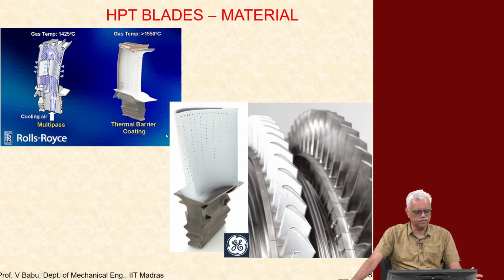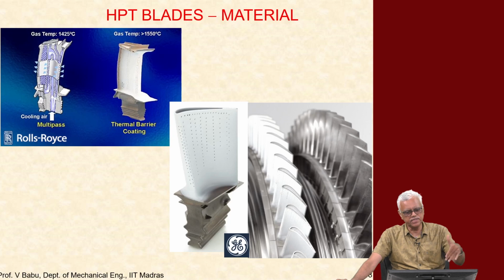So, the cooling plus the TBC. So, you can see the TBC blades, you can see the hollow blades here and also the TBC coating, and you can see the holes for film cooling here. So, this is where the air from inside the blade comes out and forms a film on the surface of the blade to provide film cooling. So, you see the film cooling, you see the fir tree, which is how the blade is mounted on the disc, and you see the blades themselves here. So, this allows the temperature to be increased. So, this will keep the temperature of the blade metal below the melting point.